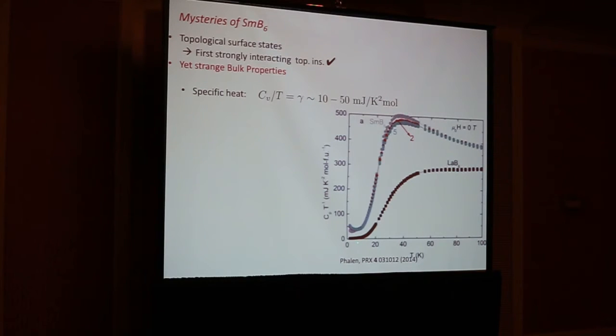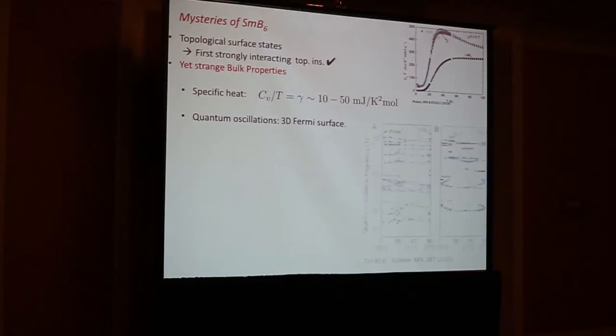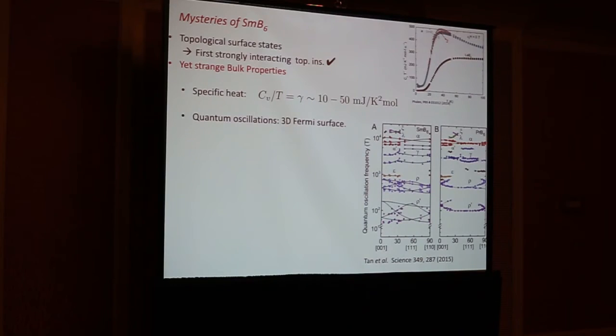Lanthanum hexaboride, which is a metal with a large Fermi surface, has a much smaller linear specific heat. That's rather remarkable, given this is an insulator. Okay. And the quantum oscillations seem to not indicate that you've got surface states. They're not sensitive to the surface states. They seem to be picking up something in the bulk. And one of the indications of this is that although the surface conductivity dominates the conductivity, you don't see Shubnikov-de Haas oscillations. No one's ever seen them in this material.